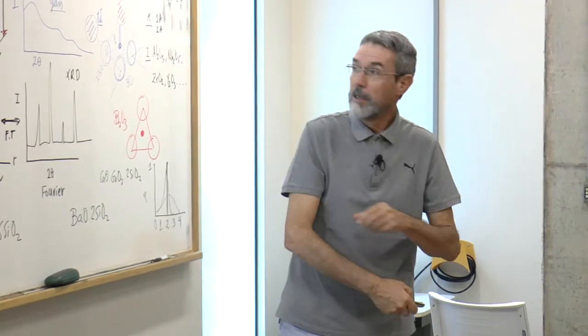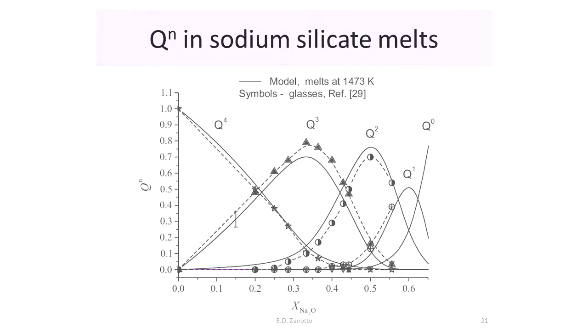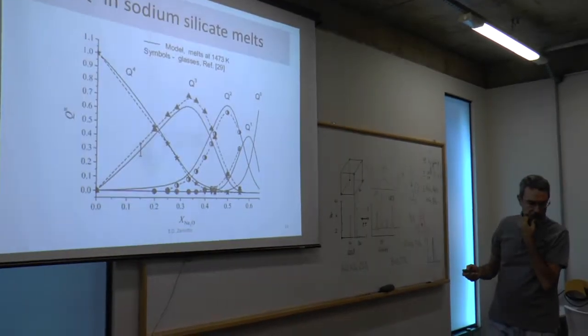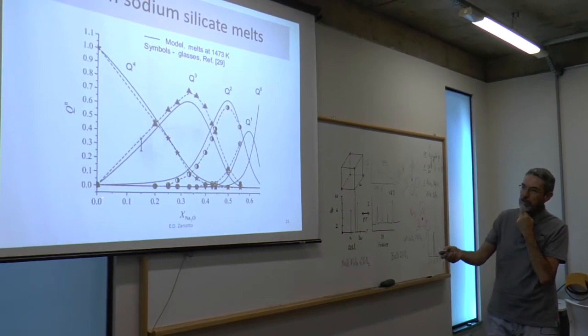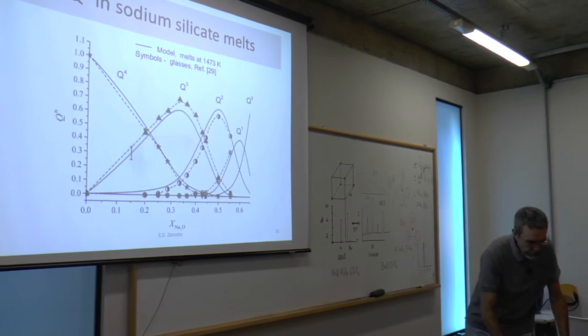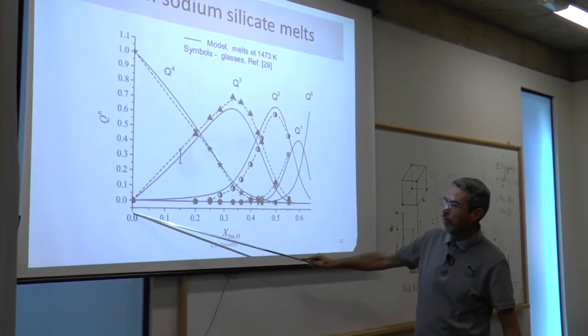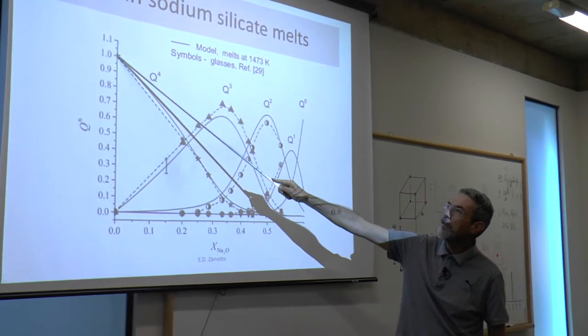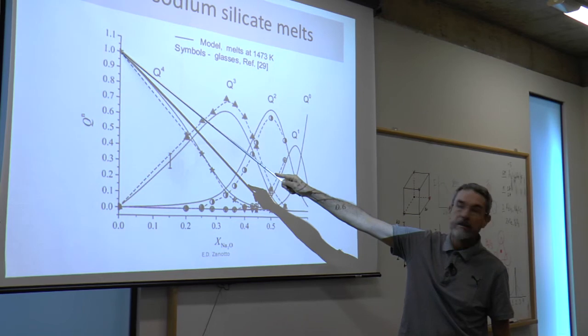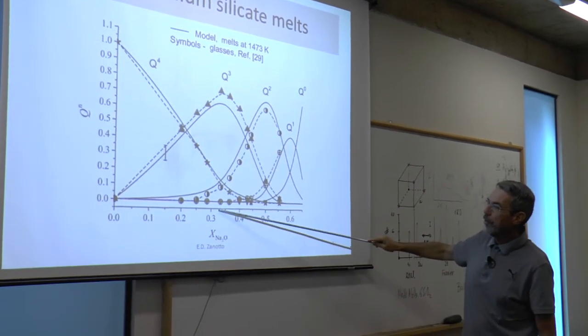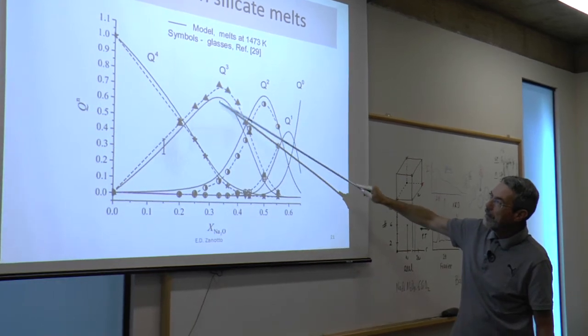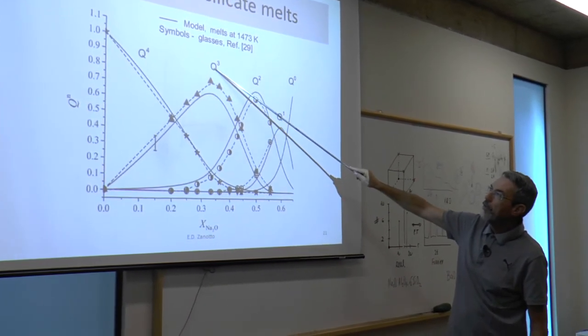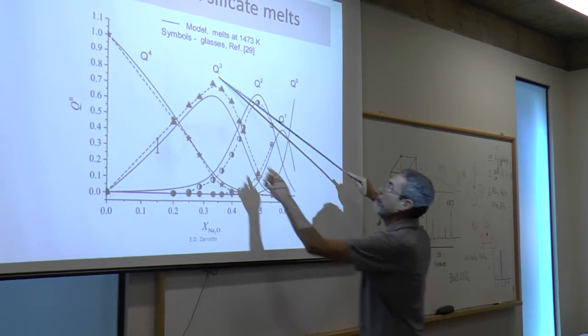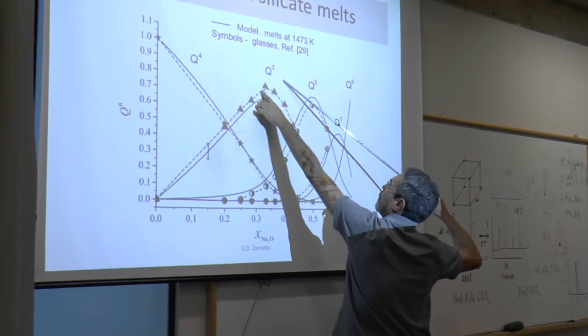Okay, let me go, oops. So this is the type of plot I was telling you. This is a QN distribution in sodium silicate melts with different fractions of sodium. So this is pure silica. Oh, pure silica is here. 0 sodium oxide is pure silica. So pure silica is 100% Q4. Okay? Now, let's take a sodium disilicate, 33% of sodium. There's a lot of Q3. By the way, this is model calculations. These are experimental data from NMR.